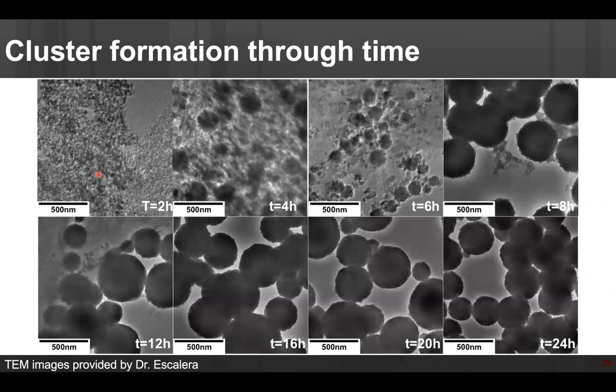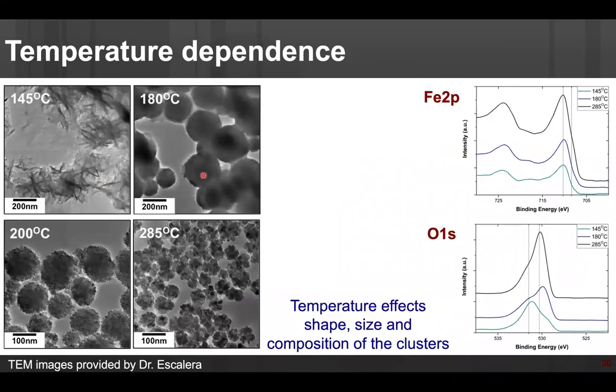One of the studies that I did is follow the synthesis through time, so I can see how the clusters are being formed, and then how with more time we get a more homogeneous distribution. We also look at different temperatures. After 180 Celsius, we can start seeing magnetite instead of iron 3 oxides. We can control the size of the cluster and the nanoparticles by changing temperature.